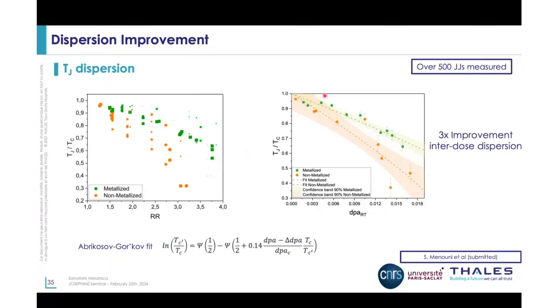We went ahead and did this second statistical analysis where we just took these points and plotted them versus the displacement per atom, as the Abrikosov-Gorkov law, which we actually fit. And we can see a clear agreement in both cases, but especially for the metallized one, we can see that the standard deviation was improving. It has improved a lot, because we can observe an improvement in the dispersion of 3 times. The same kind of analysis was done for the IC measurements, and we could see that the improvement was 1.5. So just to say that